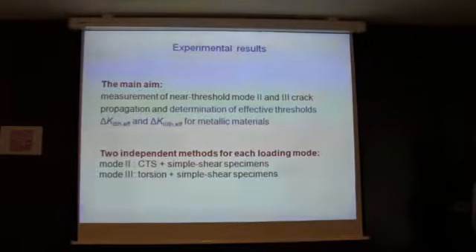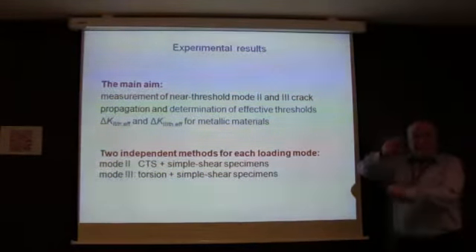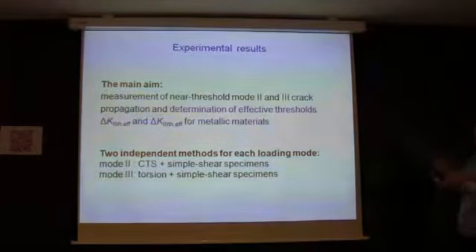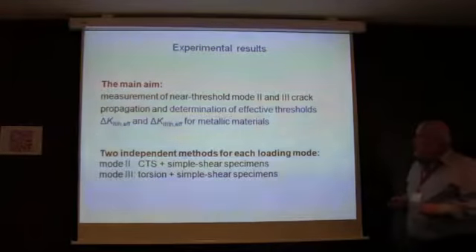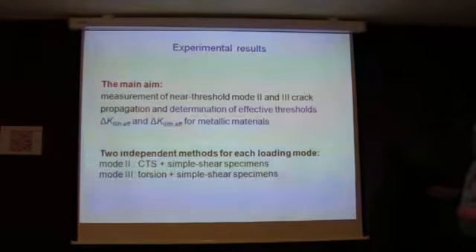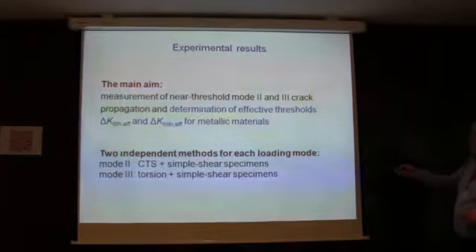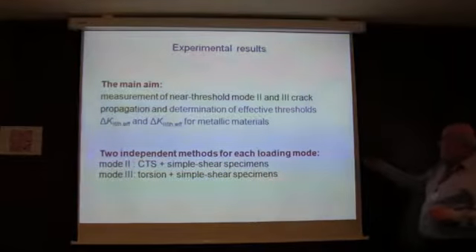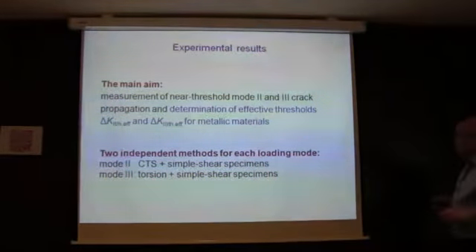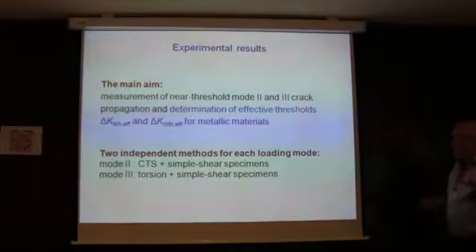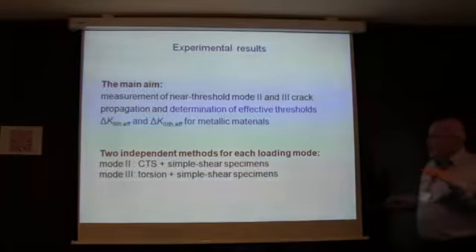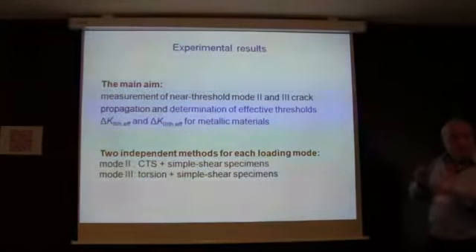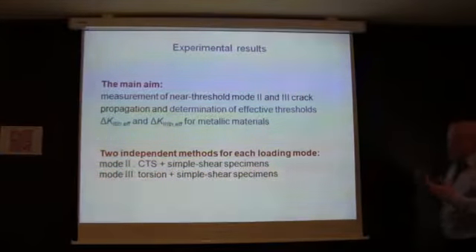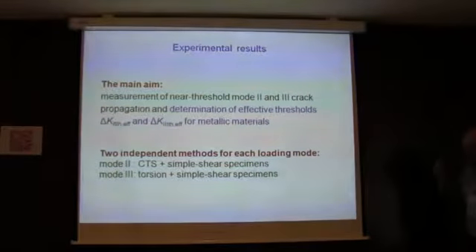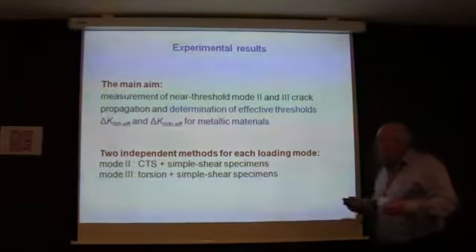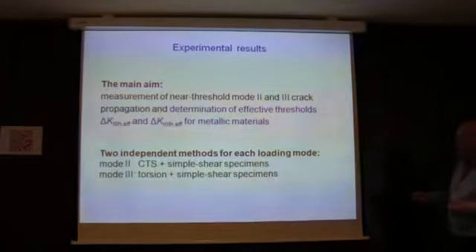There were many things made in the past with application of tensile stress to open the crack and so on. But this is always a mixed mode, and it's maybe not correct. But anyway, the main aims were the measurement of near threshold mode 3 and mode 2 propagation and determination of effective thresholds for these cases. And so we did very careful experiments for each mode, for two different geometries of specimen and cracks, so that we were sure that everything is okay, it's transferable. For mode 2, for mode 3.